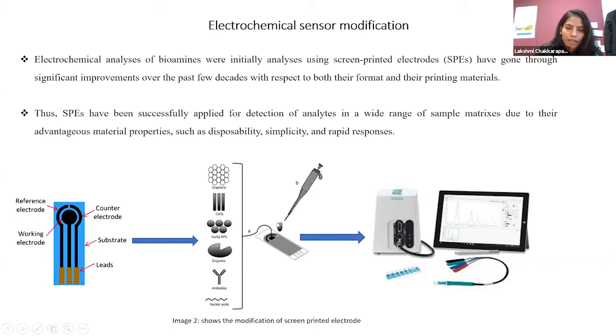And then we use a polymer material. Here I mentioned different materials. It's possible to use these materials, but in our case, we selected conductive polymers, polytoluidine blue, and we just drop cast the monomer solution over the electrode surface, exactly on the working electrode surface. The working electrode is manufactured, like printed, with carbon ink, and the counter electrode is also printed with carbon ink, but the reference electrode would be silver chloride.